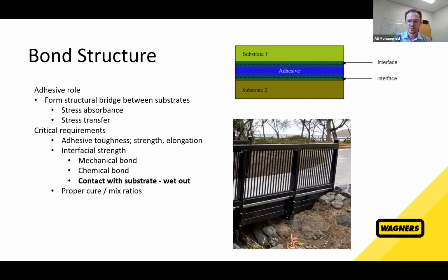Just on the right there at the bottom is how we use adhesive bonding on site. One of the ways, that's one of our bridges, and we bond some of our sections together in a laminating type setup. So at the bottom of that bridge, you can see three of our composite sections bonded together to form a 3-stack high.